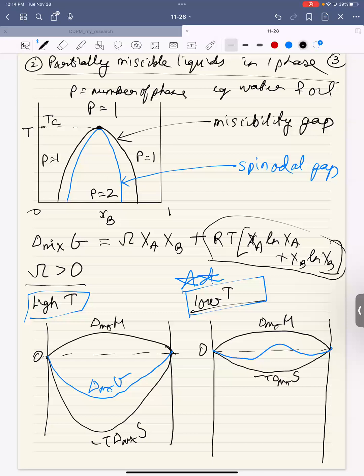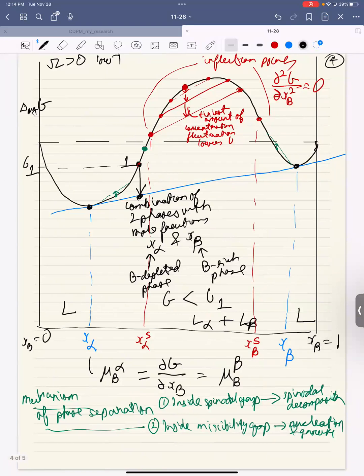And the reason the structure inside the blue one looks like a fractal is because in between these two inflection points, anytime you drop down, the overall free energy goes down. While over here, if you try to split into two concentrations, the free energy will go up, unless you have a very big fluctuation, which automatically takes you to here and here. That's nucleation and growth, okay?